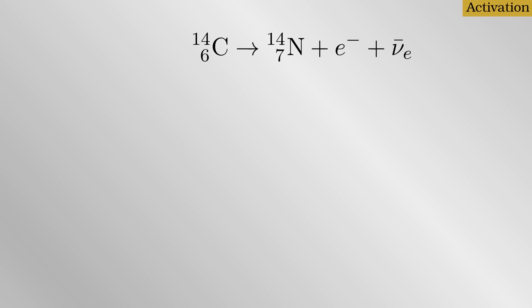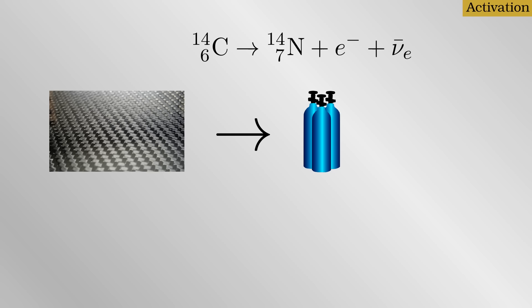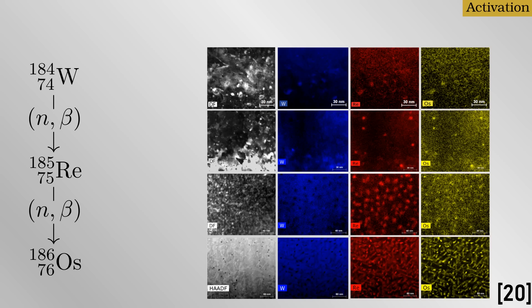The radioactivity aside, activation is a problem simply because it changes one chemical element into another, a process called transmutation. Once carbon-14 decays it becomes nitrogen, which is different chemically. If a certain proportion of the atoms which make up a material change to another chemical element, this could have an effect on the material's tensile strength, density and so on. A load bearing beam might become weaker and break. An important component might stop conducting electricity and therefore fail. Again, the diverter is one particularly vulnerable area, but so too are any diagnostic or fueling ports, mirrors in a laser inertial scheme and the like. Under neutron irradiation, tungsten transmutes to rhenium and osmium. Atoms of these two newly generated metals seem to clump together within the original structure and change the mechanical properties.